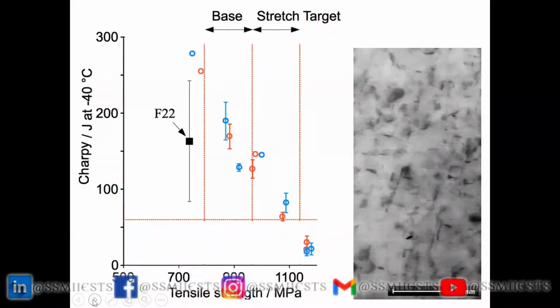So this is the normal commercial steel that BP uses. And this was the material that we created, which is higher strength and yet maintains the toughness. And there was something called a stretch target. That means how far can we go beyond this one? And remember, it's weldable, it's got to be manufacturable in very large quantities and so forth. And you can see that we have achieved, this is the target for toughness. We can achieve much higher strength, and very severe testing has been done on the hydrogen susceptibility of this material, which relies on these hydrogen traps.